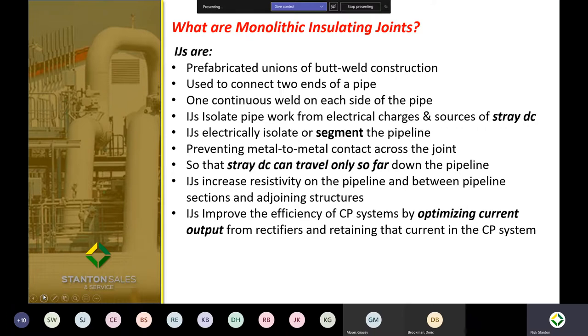So they electrically isolate or segment the pipeline. Where do sources of stray DC come from? Well, electrified railroads, nearby pump and compressor stations, mining operations, any large user of direct current, and of course, the cathodic protection system itself and the CP system of adjacent pipelines. Stray DC can be picked up by the pipeline and discharged into the soil at some distance on the pipeline. The process of discharging off the pipe and into the soil accelerates corrosion of the pipe wall at that discharge point and actually thins out the wall. That causes stray current corrosion or localized corrosion.